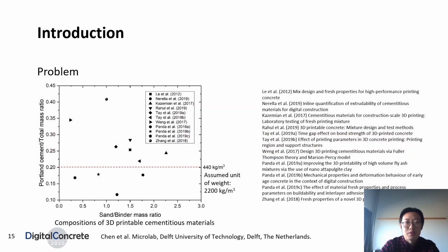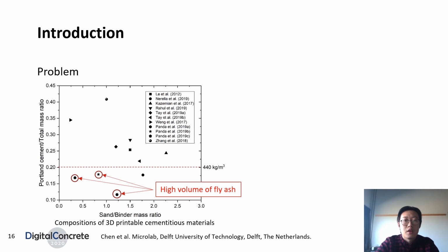However, a problem needs to be raised here. The current printable materials may contain a lot of Portland cement due to the relatively low aggregate content. In this figure, there are several mixtures containing less Portland cement, which was replaced by a high volume of fly ash. But the high volume of fly ash might result in low strength of the hardened concrete.